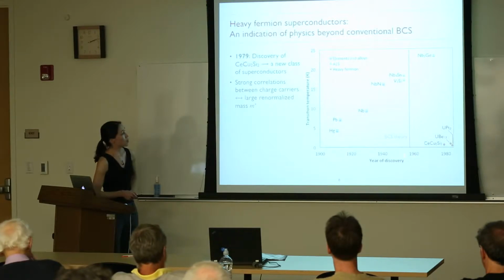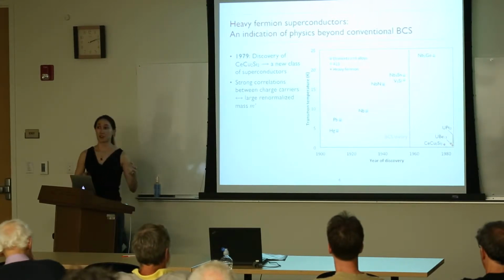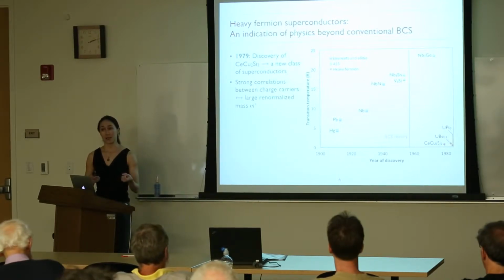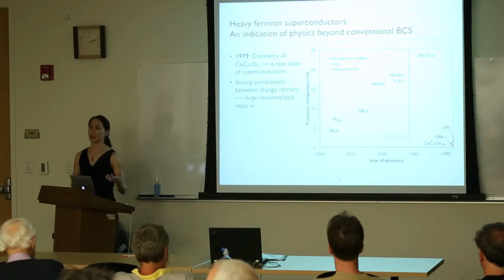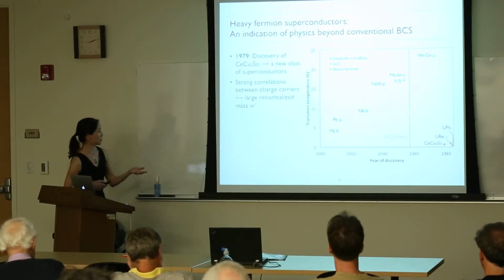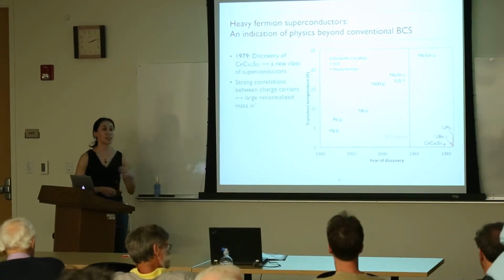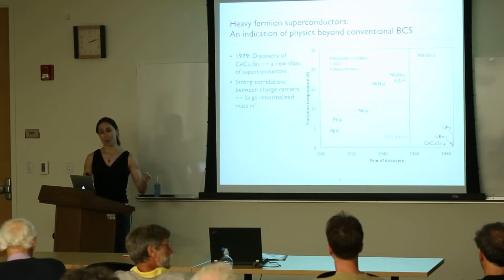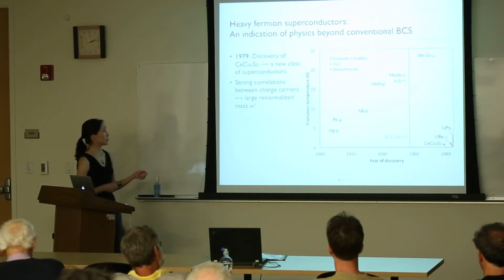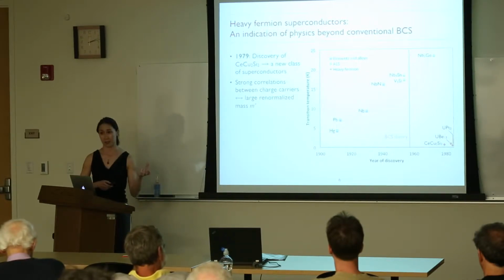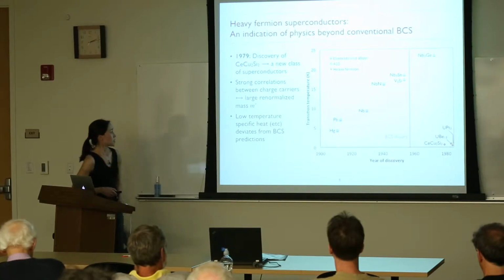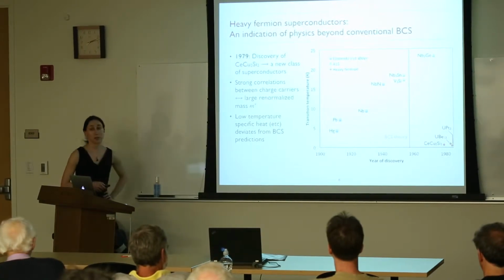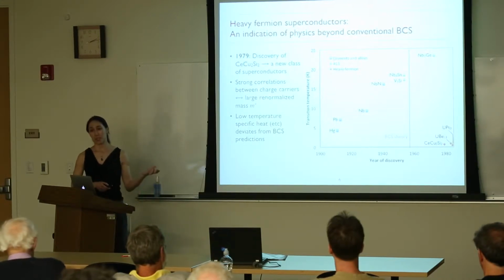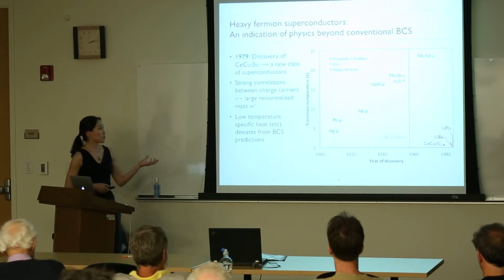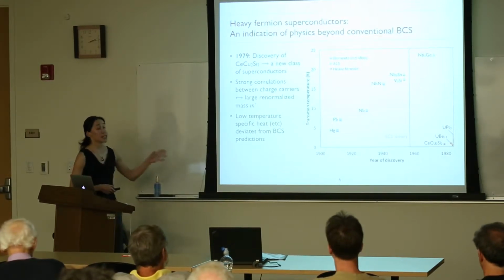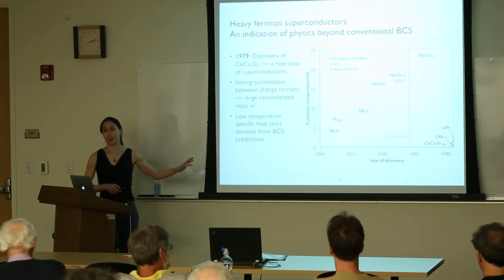One of the first things that came up with these materials is that it was found that the charge carriers, the electrons in these materials, are actually very strongly correlated to one another. So they basically act as if they're much heavier than they are in a bare sense. The reason that this is surprising is that BCS theory was predicated on the idea that the interactions between these electrons are somewhat weak. So the fact that here the electrons are interacting very strongly with one another is a surprise. The second surprise is that if you measure some quantities, for instance the low temperature specific heat, their functional form started to deviate from the predictions of BCS theory. So this was, again, another thing indicating that there was a little more to superconductors than what we understood so far.